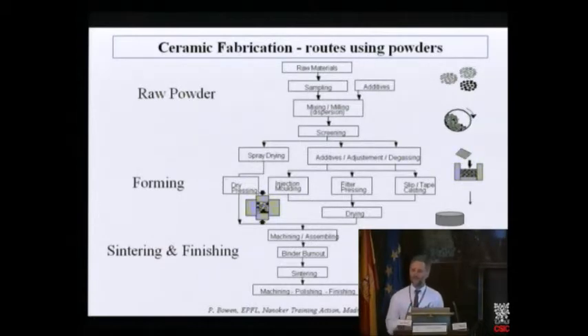Because with the cheap powder, broader size distribution, it was difficult to get the tolerances that Professor Gaddo was talking about. To get the tolerances, they had to do too much machining. The finishing cost 25% of the whole product chain. They used the expensive powder, 10 times in price, and they reduced the machining by a factor of 2, and the whole process was cheaper using a powder that was 10 times more expensive. So quality powder counts.